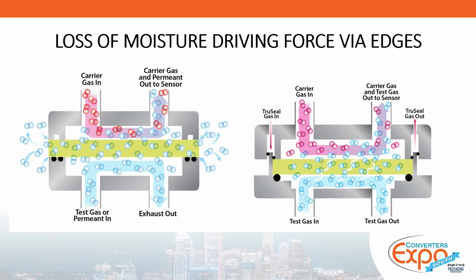So to remedy this situation of the moisture loss through the edges, this schematic here shows a good example of a film test, a flat film in a diffusion cell. And the one on the left, you see it has a lot of edge diffusion. And the one on the right is actually a modified cell that covers the edges. So essentially that forces any moisture that you're going to see by the detector, you know that that's moisture that actually permeated through the coating and was not compromised by atmospheric effects.